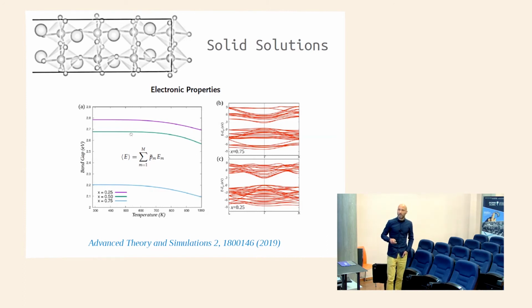also fulfill the right magnitude for the energy bandgap. Not only this, we also found out by looking at the electronic band structure that these energy bandgaps were direct, right? So they were just kind of luckily inheriting the direct bandgap from the zinc sulfide, and on the other hand, they were inheriting the small bandgap from the gallium phosphide.